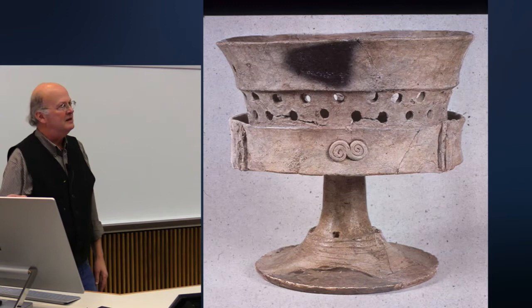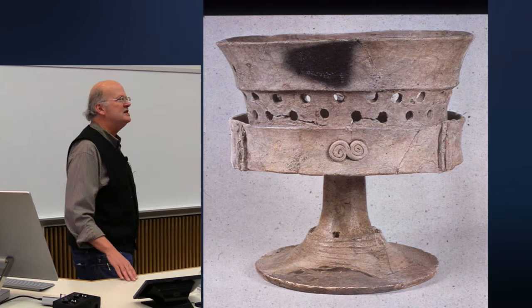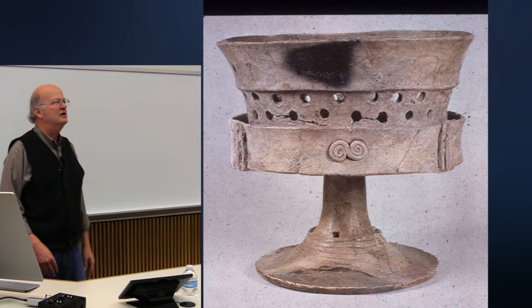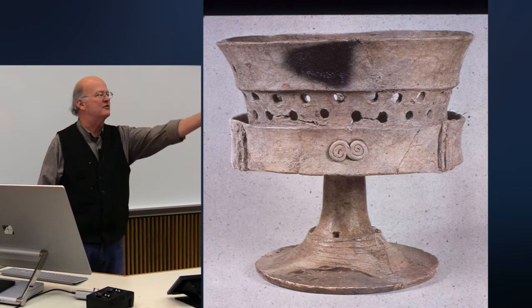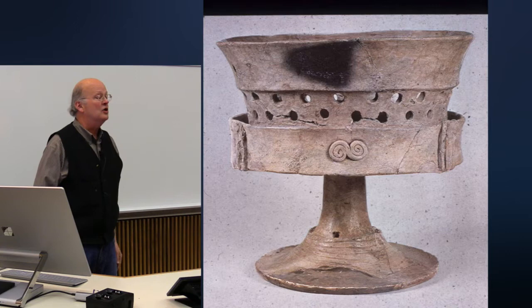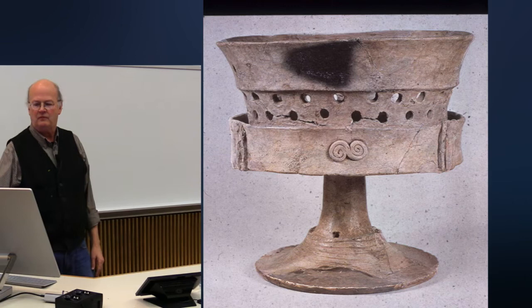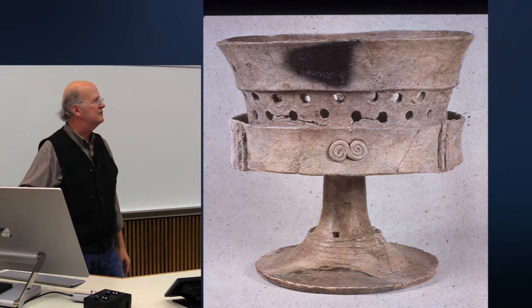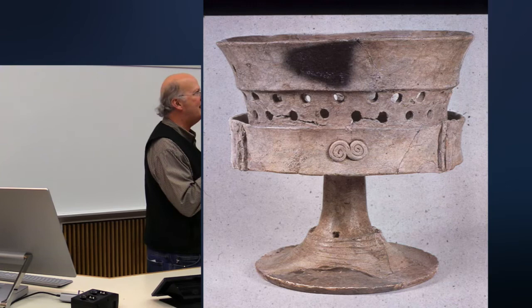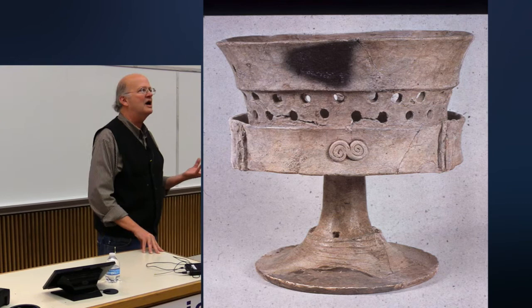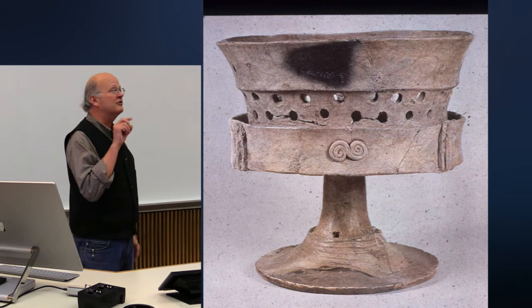Along about 1,500 years ago, maybe a little longer, new technology, though, came to Japan from the Korean Peninsula. In point of fact, it actually came from China originally, through the Korean Peninsula and then to Japan, for a new design kiln. And what happens is you see the color changes. You see a lot more of this kind of dense gray color, and it is much harder. That word dense is important here, because if you were to tap this, it would ring. Whereas the earlier pots, which were not fired to such a high temperature, would go thunk, thunk, thunk, like an earthenware flower pot.